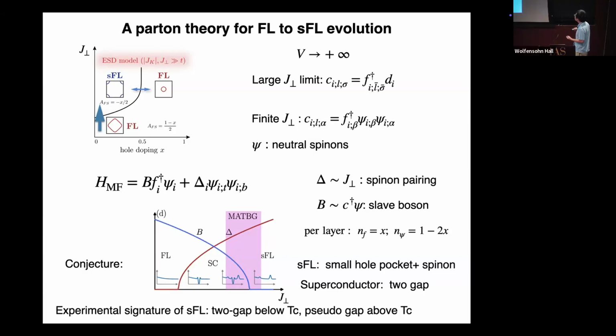And how do you go to the Fermi liquid? It turned out to go to the Fermi liquid in this framework, you need to introduce this b as f dagger psi. So this b turned out to be just the bound state of electron and the spinon. It's actually the same as the b in Subir's talk. So it's the slave boson. So the hope, my intuition is at a smaller J-perp, this slave boson condenses. At the other limit, delta condenses. Then we get these two normal states.